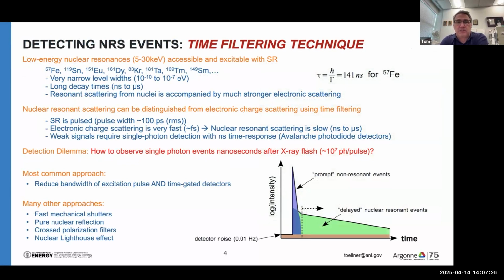And this gives them a long decay time, typically nanoseconds to hundreds of nanoseconds. In the case of iron 57, the nuclear level lifetime is 141 nanoseconds. And this is the primary aspect that we exploit to separate these events. So the synchrotron radiation is pulsed, and the pulse width is typically a couple hundred picoseconds at the APS post-upgrade. This is very narrow compared to the lifetime, and so this allows the possibility to do time discrimination.